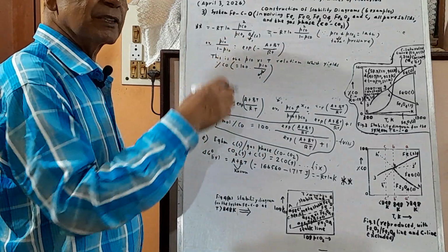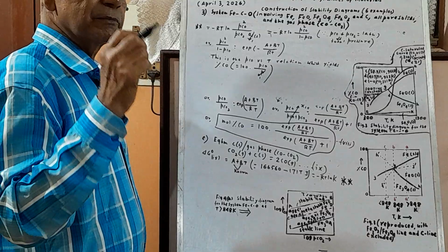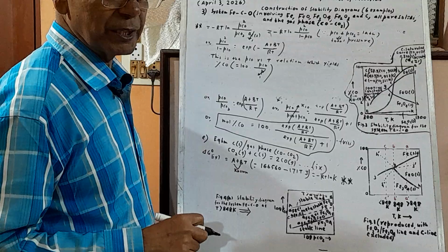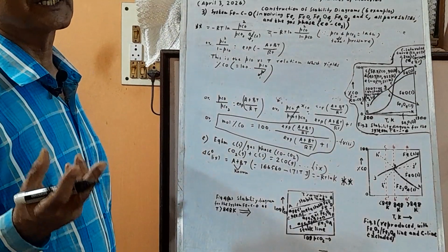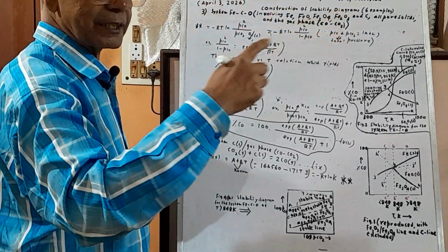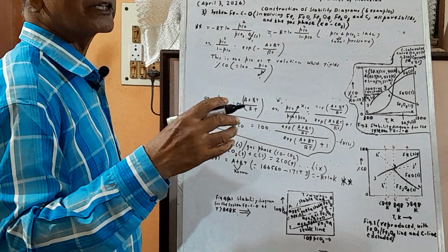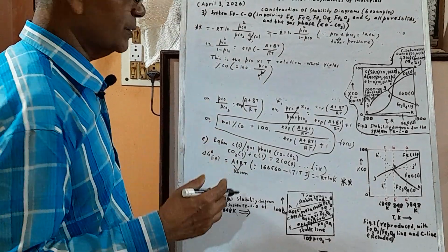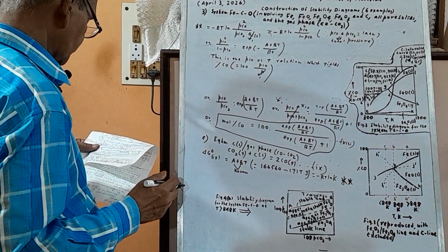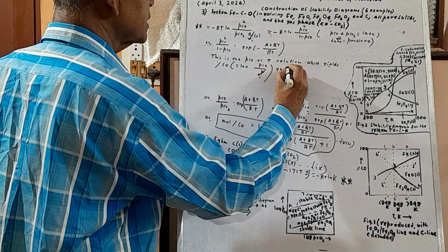Choosing some temperature, you can always get this. This is a quadratic equation in PCO, given the temperature, and you get the value of PCO and percentage CO for that temperature. So again you get percentage CO versus T for a number of cases, then generalize the equation. Anyway, I am giving the outline: percentage CO versus T relation.